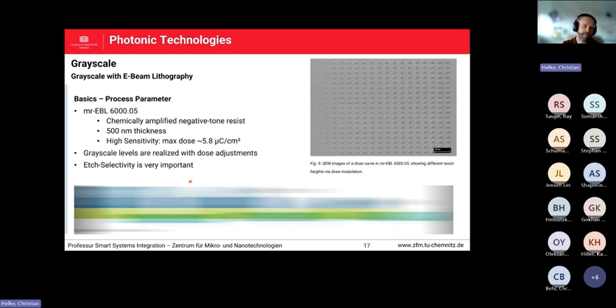So here again, this one is the negative tone photoresist we also use for mix and match. It's the mr-EBL 6000.05 with 500 nanometer thickness again, and this high sensitivity. I mentioned before the 1.5 microcoulomb per square centimeter. Here we reach this down to 6 microcoulomb per square centimeter to get the complete 500 nanometer photoresist cross-linked and exposed. Again, gray levels here are realized with dose adjustment in between layers.